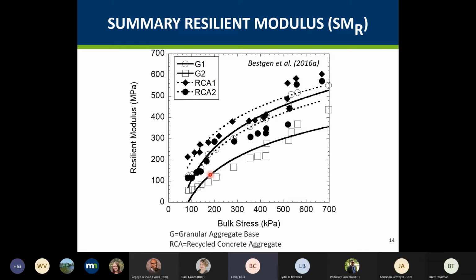So your resilient modulus value of your material will change depending on the confining stress and the vertical loading stress that you apply. We call as a bulk stress the sum of the confining pressure and the dynamic deviator load, the vertical load that you apply, simulating the vehicle load. So what is the summary resilient modulus? There are multiple different resilient modulus values for your materials, and what you need is a single value to use in pavement ME.